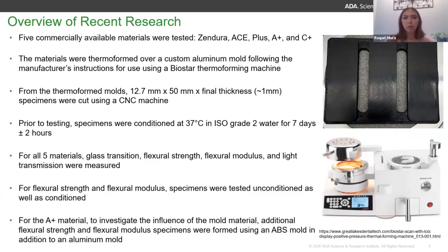So an overview of the research we've done so far: we tested 5 commercially available materials: Zendura, ACE, Plus, A+, and C+. These materials were thermoformed over a custom aluminum mold using the manufacturer's instructions and a BioStar thermoforming machine. From our thermoformed molds, we cut 12.7 millimeter by 50 millimeter by approximately 1 millimeter thick specimens using a CNC. Prior to testing, we conditioned them at 37 degrees Celsius in ISO grade 2 water for 7 days, plus or minus 2 hours.